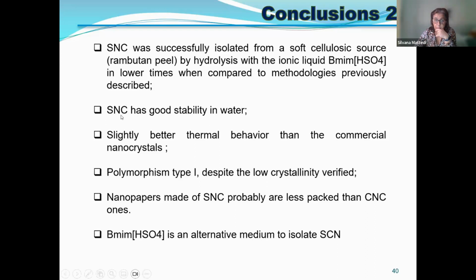The spherical has good stability in water. We have a slightly better thermal behavior than the commercial nanocrystals. That is interesting. The cellulose present is polymorph cellulose type I, although we have a low crystallinity for the paper. The nanopaper is probably less packed than the cylindrical nanopaper made using sulfuric acid. And so this ionic liquid is an alternative medium to isolate spherical nanocellulose.